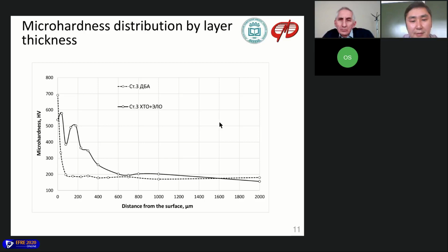affects like pulse values and results in some soft phases depending on its frequency. So we obtain soft and hard phases depending on the thickness of the layer. But I think this local minimum of around 400 HV probably relates to the phase composition. So on this distance from the surface of around 50 micrometers, probably the majority of the soft phases concentrate on this thickness.